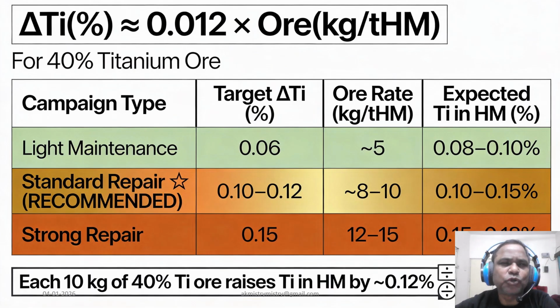So how much ore do we need? Using 40% titanium ore, we use the formula: delta Ti is equal to 0.012 times ore in terms of kg per ton hot metal, that is the titanium ferrous ore. For a standard repair, which is our recommended path, we target an ore rate of 8 to 10 kg per ton of hot metal. This typically results in a titanium concentration of 0.1 to 0.15% in the final hot metal. It is of course away from the level which we have shown, but here the operator or blast furnace team must be very careful.